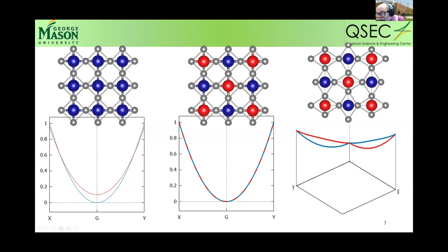So you can see that this is the same octahedron, well, in this case, rhombus, the same diamond around each metal atom, but they are rotating, they are staggered. So now, even without magnetism, my unit cell is doubled, and it has two metal atoms. And there is a symmetry operation. It's actually a rotation axis here, but it's not inversion symmetry. So there is no inversion symmetry operation which maps one spin onto the other.